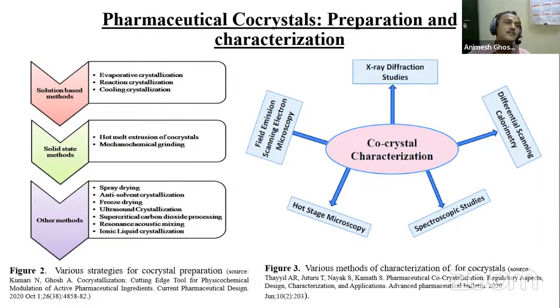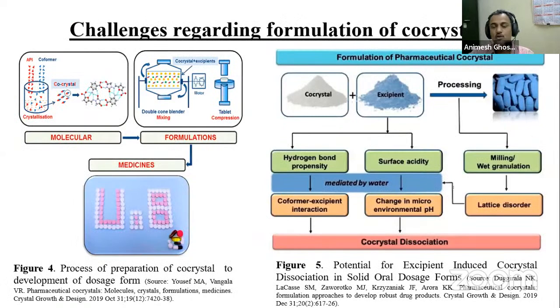So what are the different characterization techniques? The most important is X-ray diffraction. In X-ray diffraction, there are two types: single crystal X-ray diffraction and powder X-ray diffraction. Most importantly, if you would like to characterize a co-crystal, the best way is to get the single crystal and characterize it using single crystal X-ray crystallography. Then DSC, spectroscopic studies like FTIR and Raman, hot stage microscopy, and field emission scanning electron microscopy.